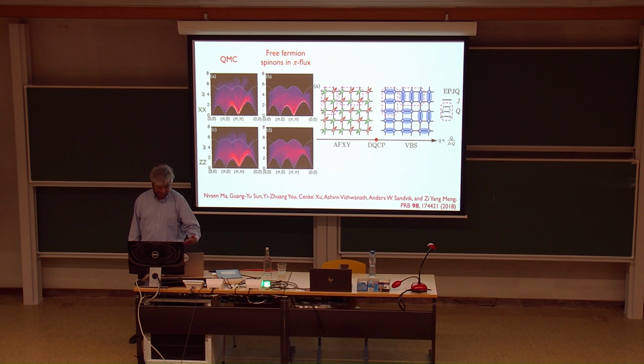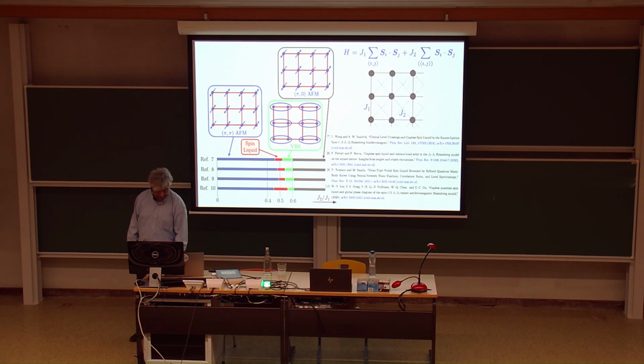And there's some numerical evidence supporting this picture in terms of the spectrum. So in fact, this is some numerical data of this transition in quantum Monte Carlo. And this is just a comparison with free fermions moving in pi-flux. That does a beautiful job. And this is, you take a more realistic model, J1 and J2 exchange interactions, and you indeed find Néel order and valence bond solid order in some intermediate window of spin liquid, gapless spin liquid type behavior with Dirac spectrum of spin-ons.